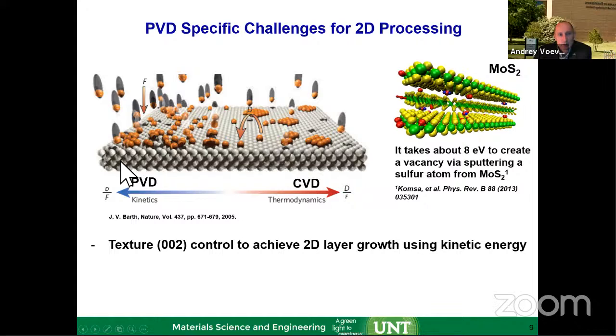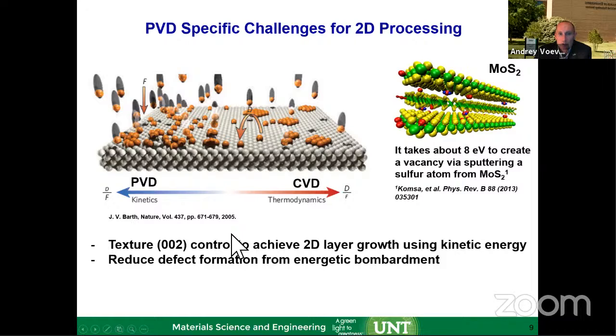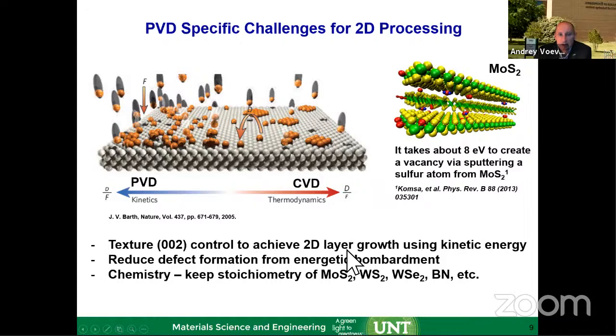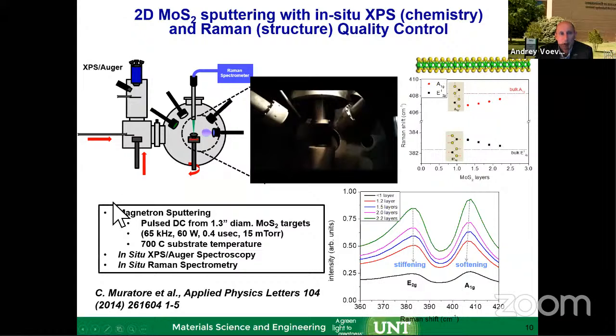To tweak the process, over time you learn how to control the growth in the direct growth deposition, making the 002 planar surface parallel, and how to reduce defect formation by controlling energetic bombardment. And then keep the stoichiometry. Sulfur easily combines with oxygen and hydrogen and is evacuated from a vacuum chamber. So keeping the molybdenum to sulfur 1:2 ratio is important to achieve the electronic properties. That was also learned through this.